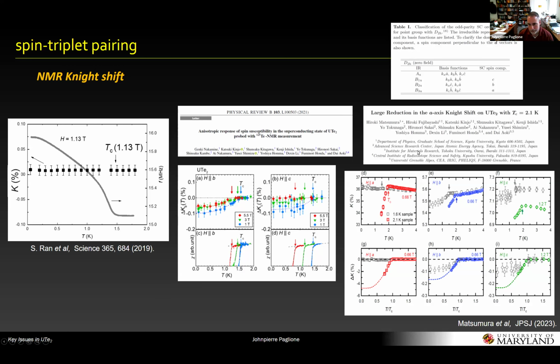Okay, so there are claims from these results. For instance, they claim this is only consistent with a fully gapped superconducting state, and so I would not tend to agree with that result unless we do further experiments to really understand the effect of surface states and so on.